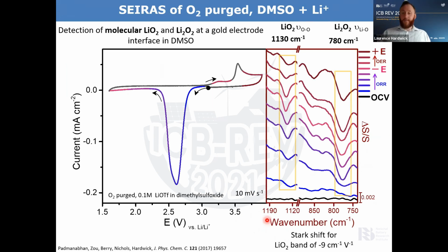So if we look at the oxygen reduction and evolution reaction in the presence of lithium, here we have our cyclic voltammogram showing this. We have lithium triflate in dimethyl sulfoxide, and here's our initial spectrum. It's a little bit wavy, but essentially it's flat. This is our open circuit potential, and as we reduce the potential, we see our redox peak where oxygen has been reduced, and we start to see some negative going peaks. This means something is appearing, something is growing that wasn't there previously at the interface.